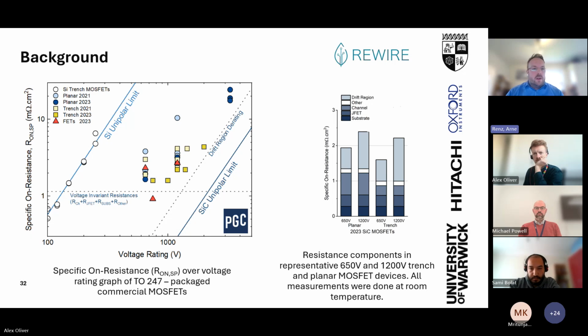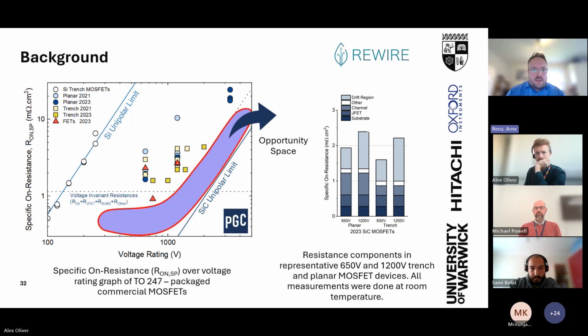And you see the silicon carbide unipolar limit. On the silicon unipolar limit, you see that the devices that we can measure, the commercial off-the-shelf devices, sit more or less on or even slightly below the unipolar limit. For silicon carbide, more towards the right-hand side of the graph, that is not the case. And Alex, if you just click once. So what we see here is a huge opportunity space in which we can think about ways to further push the technology towards its technological limit, towards the unipolar limit. And then on the right-hand side, where we plot specific on-resistance components for technology that's currently on the market, you see that the channel is a huge proportion of this.